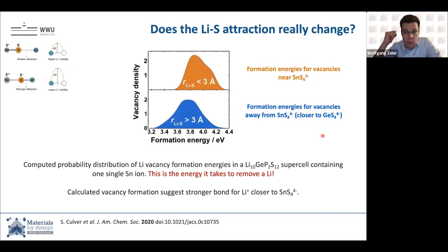And naively, one would say, okay, the more energy it takes to take it out, the stronger it is bound. Now we used a cutoff of 3 angstroms, looking at all of the lithium that is further away than 3 angstroms from that tin site, and all of the lithium that is closer than 3 angstroms away from this tin sulfur polyhedron. In orange is everything that is closer to this tin site, and the lithium that are closer to the tin site have a higher formation energy. So it really seems like the lithium is stronger bound to the tin S4 tetrahedron than to the germanium tetrahedron.